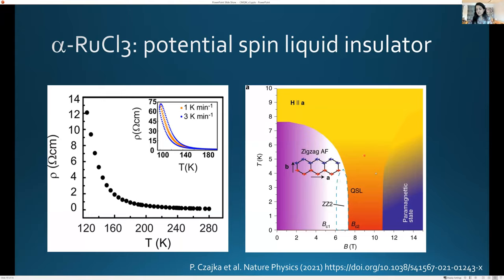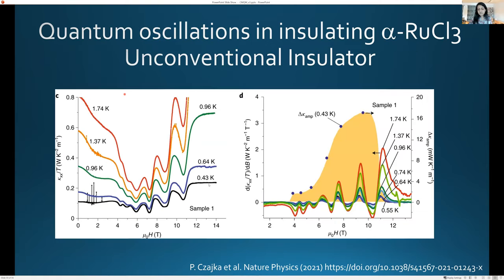It's been hypothesized as a spin liquid in this intermediate field range, 6 Tesla to 12 Tesla. And this is the range in which quantum oscillations have been reported. So they are reported to be most prominent in the intermediate field range where the spin liquid is seen. And they're also reported to have fairly low frequencies. So this is a temperature dependence, fairly low frequencies of about hundreds of Tesla and masses of a few electron masses. So in some sense, it seems like the Fermi surface and the field dependent properties of each of these materials is quite different. So in this case, the amplitude dies beyond a certain magnetic field.